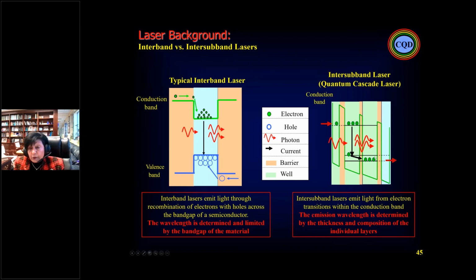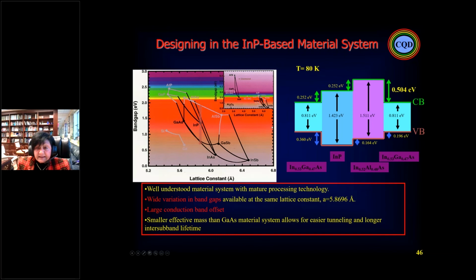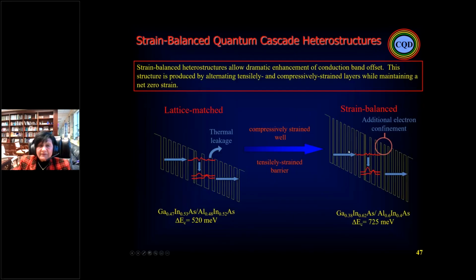But when we go to the longer wavelength, it becomes intersubband. And for intersubband, again, we can use indium phosphide material, gallium indium arsenide, exactly. And at the same time we do strain balancing, which means manipulating the structure to get exactly the wavelength that we want and the performance.